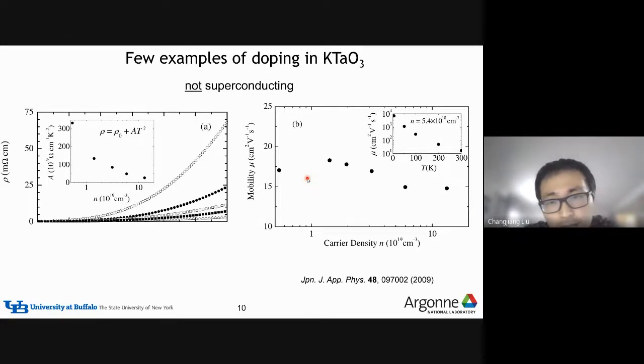In STO, people found that one can dope STO, and then the STO can become very conducting at low temperature. STO can be superconducting at a temperature below 0.5 Kelvin. So people also investigated the doping effect in KTO, but surprisingly, people were not able to see any signs of superconductivity in KTO. So these are the early studies of the effect of doping in KTO. They can see a metallic behavior at a doping level of 10 to the 19th per centimeter cubed, while they did not see any sign of superconductivity at the lowest temperature.